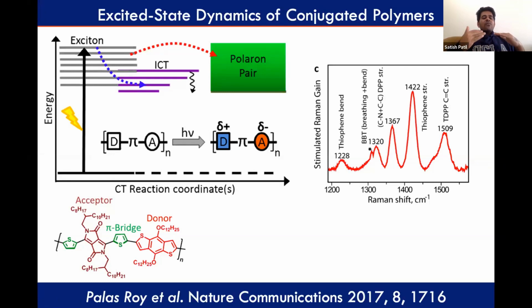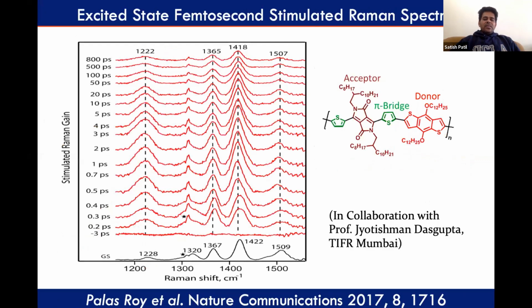And then we wanted to see what kind of geometry this polymer adopts in the ground state and in the excited state, because it is indeed very important to understand the geometry of the polymer in the excited state. So we looked at it using femtosecond stimulated Raman spectroscopy, and if I want to highlight these two peaks here, we see that the width of these peaks changes, and indeed we have found that. So this is a very important fundamental research for providing design principles. What we learned from this research is you need to have a very rigid backbone, because the polymer indeed adopts a different geometry in the excited state to the ground state.